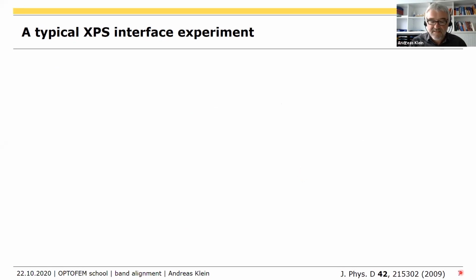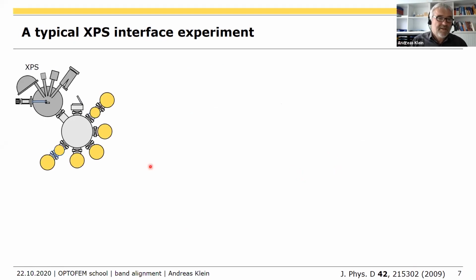This is the reference for certain specific experiments that will pop up there. So we have an XPS system. This is a monochromator, so we get a nicer, sharper X-ray line, and this is our electron analyzer. This is some other equipment. This is our sample distribution chamber, a load lock, and then we have several deposition chambers for material. So we bring our material into one of the chambers, and if we have an oxide, we heat it a little bit in vacuum or with some oxygen, and then we have a clean surface.